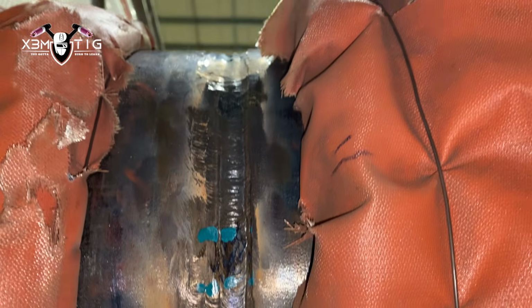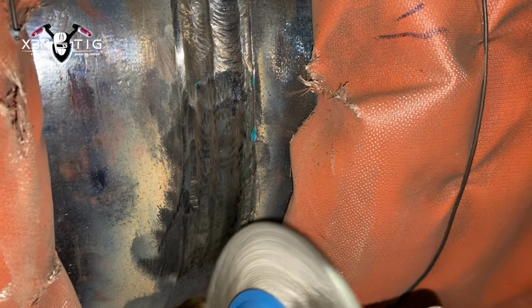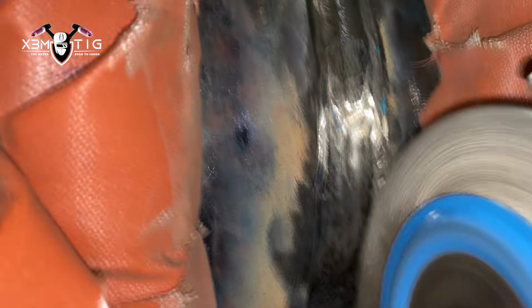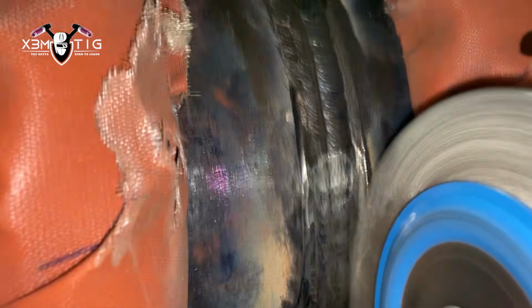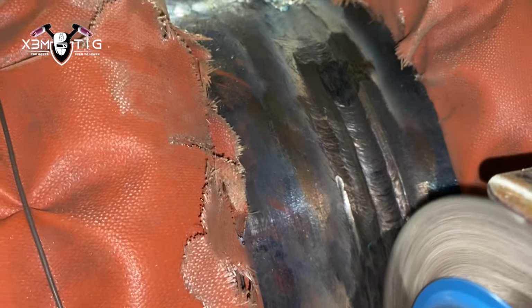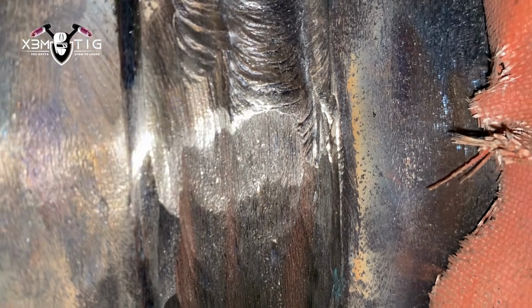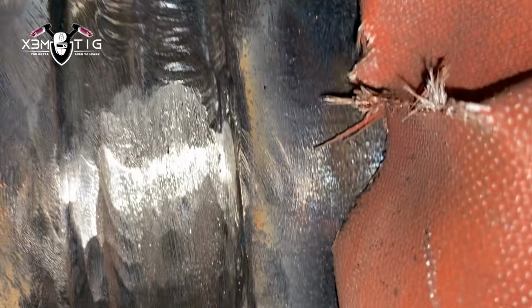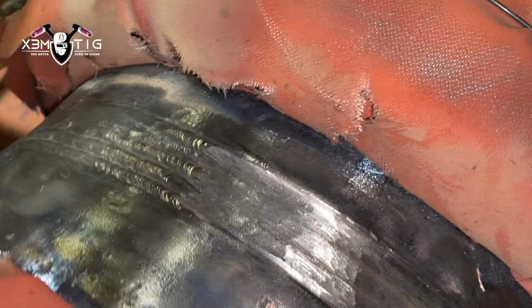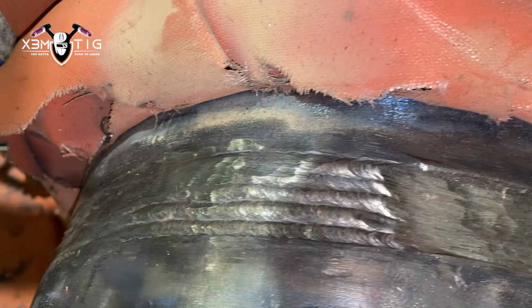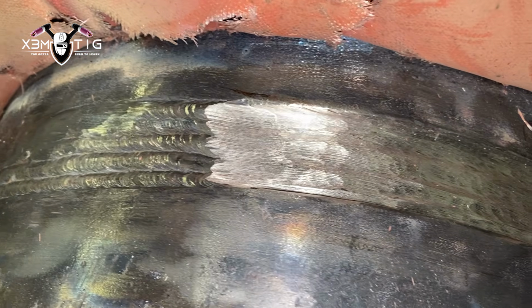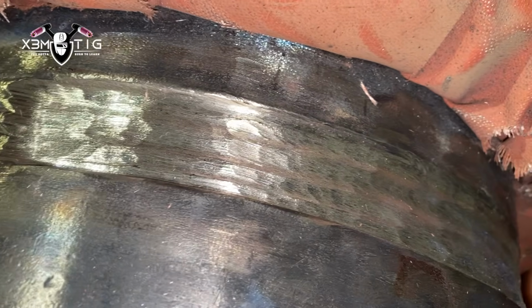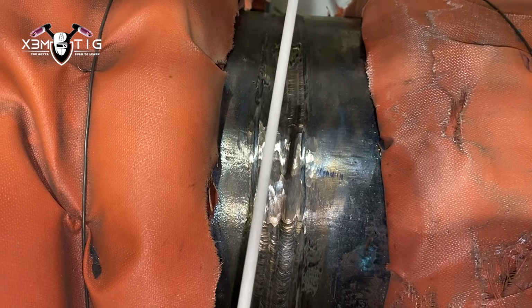So I got some indications from the QC to get rid of. They found some slag and porosity. So I'm going to take a grinder, clean everything with a wire wheel and a grinding disc. This is a little tip: use a wire wheel and make sure everything is nice and clean, because after you run a wire wheel, you can see if there's anything left. As you can see here, a couple of spots, that's slag. Definitely they want to get rid of that because it's going to show on X-ray. I'm just going to fill to flush, clean again. When everything is nice and shiny, I'm going to finish with the passes.